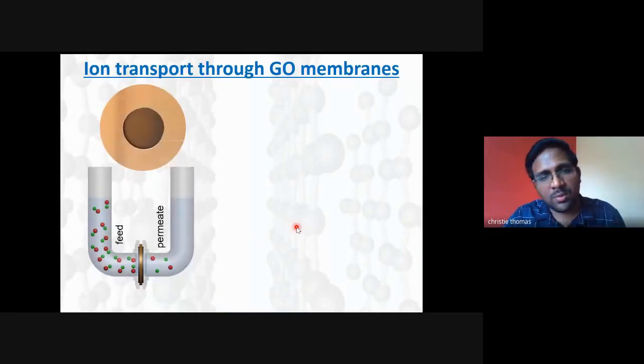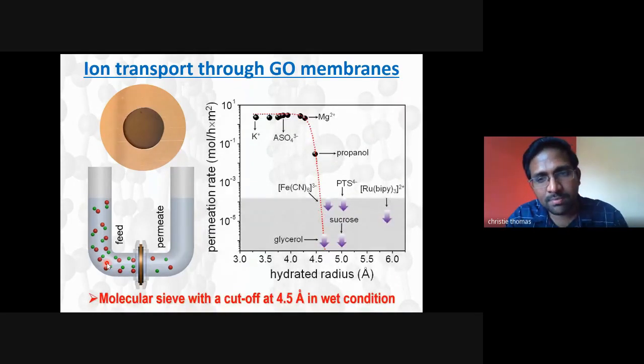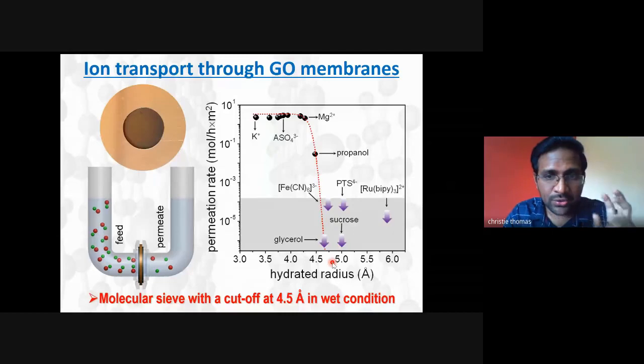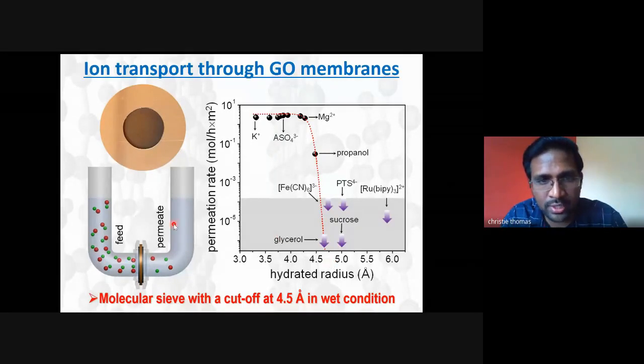Okay, so this is a typical experiment we do. We make a graphene oxide membrane. You can also do this. Make a U-tube setup, and the graphene oxide membrane is kept in between, as you see here. On one side there will be the feed, and on the other side the permeate. The feed will have ionic salt solutions. The x-axis is the hydrated radius of the different ions or salts we used, and the y-axis shows the permeation rate.